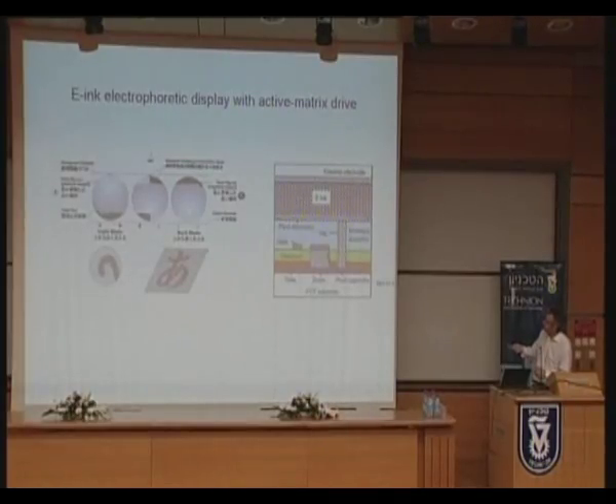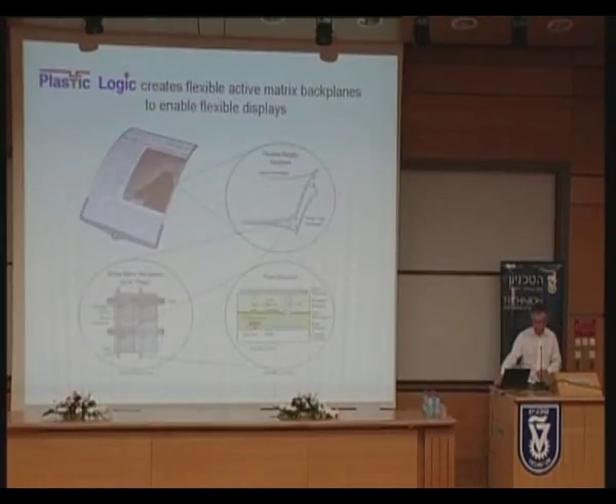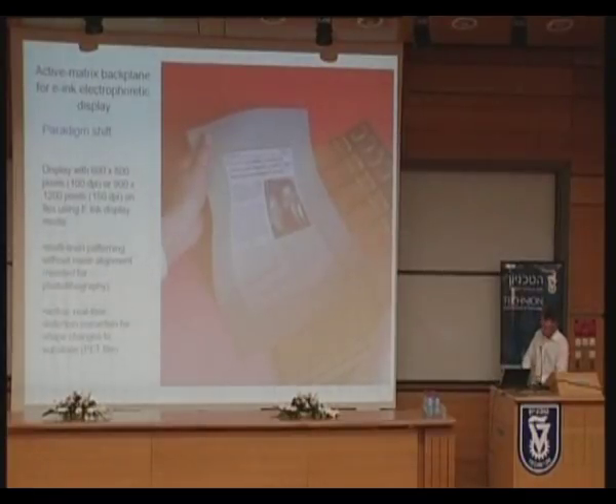There is a significant challenge to get layer-to-layer organized. We have to do in-plane patterning, and we have to be able to get registration from one layer to the next, and those are significant challenges. But when we've done that, we can then laminate our transistors, printed on a Coke bottle substrate, polyethylene terephthalate, with the e-ink foil, and then we have a paper-like display, which is not a mock-up, that is a display.